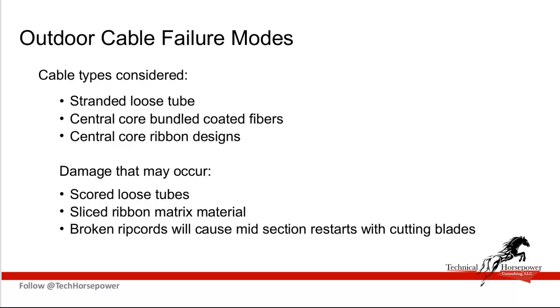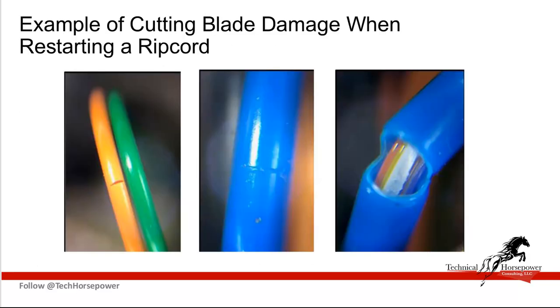We'll talk a little bit more about stranded loose tube cable failures, central core bundled fibers, and ribbons. In many cases, we would score loose tubes. And that occurs when you are trying to cut the jacket off, or if you're not using a ripcord, you're just slicing it to get where you need to be. And you can slice a loose tube, the ribbon matrix material, or even the fiber optic coatings on the fibers. And if a ripcord breaks and causes someone to create a new start, they take the knife, they ring the cable trying to get to the ripcord again, and they will typically score the cable. This is a good example of cutting blade damage when restarting a ripcord.